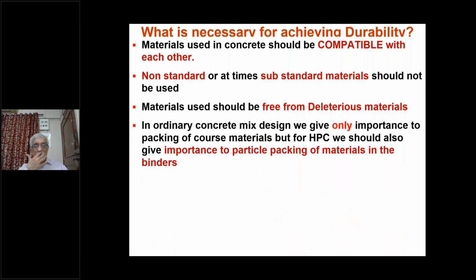In ordinary concrete mix design, we give importance only to packing of the coarse material. That means the bigger size aggregate goes into the finer size material, and you get a nice compact skeleton of aggregates. But in high performance concrete, we should also give importance to the particle packing of materials in the binders. The cement is the coarsest binder, and the microsilica, or what we call silica fume, will be the finest one. But there are others now available in the market, the ultrafine slag and the ultrafine fly ash. They are excellent packing materials.